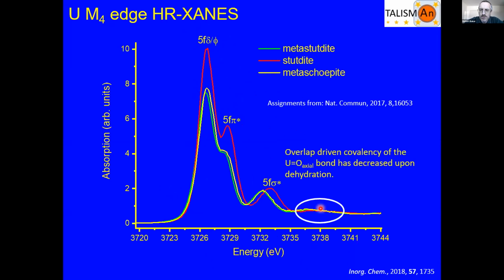You also note that there's this small transition here, which is not reproduced in any of the calculations we have done. We're not really sure what it is either. But we can see that there's a shift in the 5f sigma star transition. And from some assignments that were done by Tonya in uranium, neptunium, and plutonium complexes, this shift says that there's a change in the covalency of the UO bond. And this is the change in the overlap-driven covalency, so how the f and the p orbitals overlap with each other. So when we remove this water of crystallization, we change the covalency of the UO bond, which again is really quite surprising.